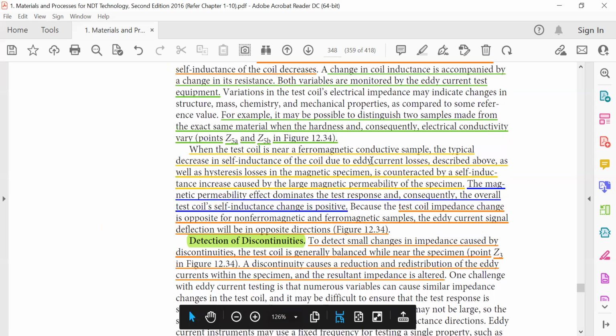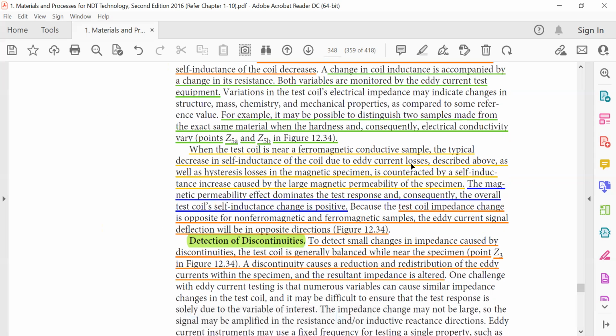When the test coil is near a ferromagnetic conductive sample, the typical decrease of self-inductance in the coil due to eddy current loss described above, as well as hysteresis losses in the magnetic specimen, is countered by a self-inductance increase caused by the large magnetic permeability of the specimen. So near a ferromagnetic, it will increase. Why? The permeability. The magnetic permeability effect dominates the test response, and consequently the overall test coil's self-inductance change is positive. So test coil impedance change is opposite for non-ferromagnetic and ferromagnetic samples. The eddy current signal deflection will be in opposite directions.